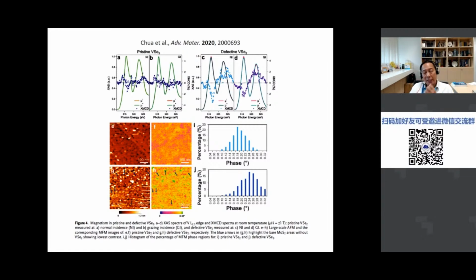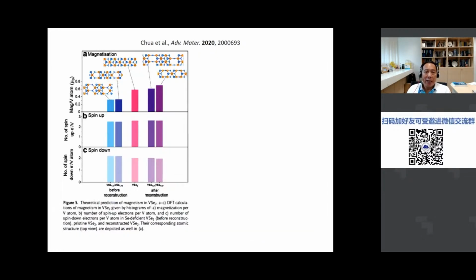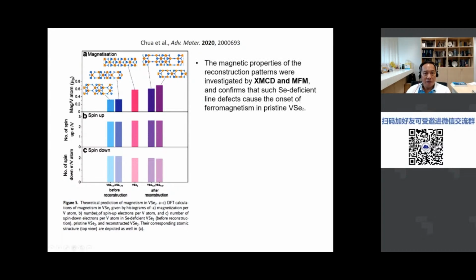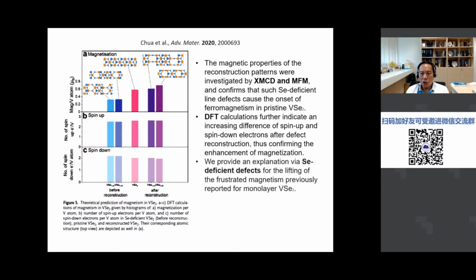So we believe that this has provided direct evidence of the effect of defects on what is probably an intrinsic non-ferromagnetic material, vanadium Se2. We did some computations as well, with a collaborator, and observed that if you move towards the more defective surface, you can actually increase the magnetization per unit atom. So the DFT supports this, and hence we propose this explanation in this paper: the reason for selenium deficient defects lifting the original frustrated magnetism previously reported for monolayer vanadium Se2.